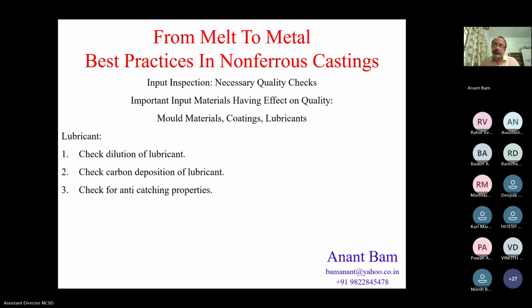Lubricants. For high pressure die casting, everybody is using lubricant. The main function of lubricant is again to prevent soldering, and the secondary function is to have thermal balance of the die surface. Even today, the majority of foundries are using mineral oil as the basic lubricant, emulsified in water, maybe 1%, 2%, 5%. The dilution depends on the manufacturer's recommendation and intricacy of your casting.